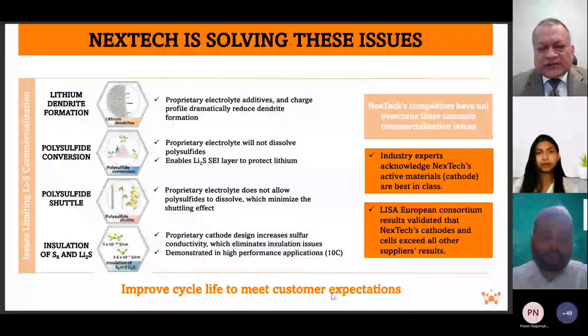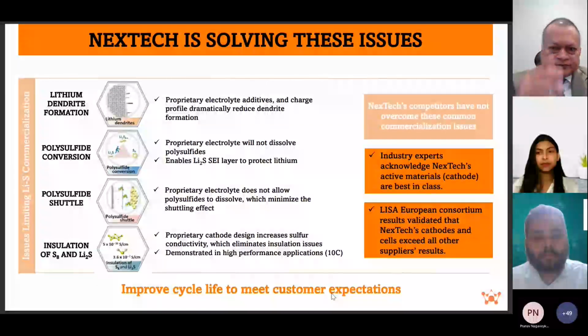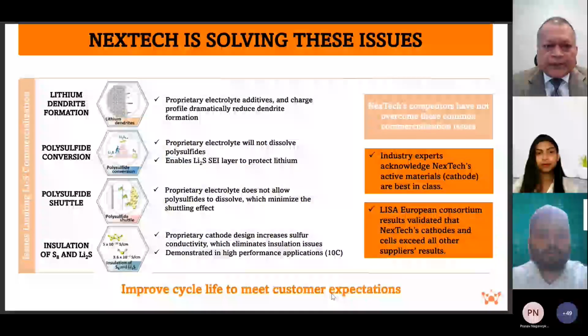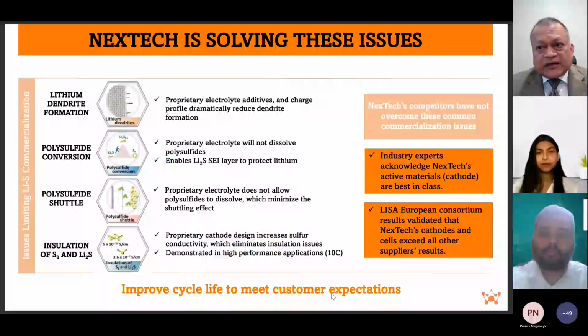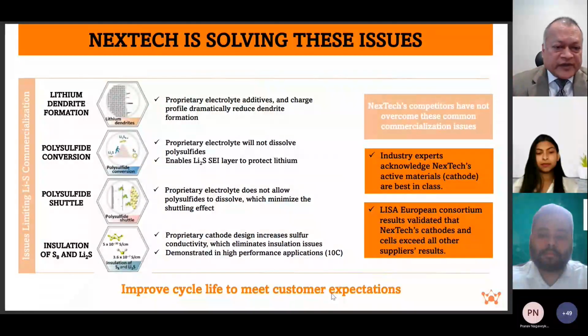Here are the traditional issues with lithium sulfur systems. You have dendrite formation, which basically pokes holes through the separator and shorts the battery out. And we are developing and have developed electrolyte additives, looking at different electrolytes, and also adjusted the charge profile dramatically to reduce dendrite formation. And we are looking at pulse charging to break up any dendrites when they form initially.